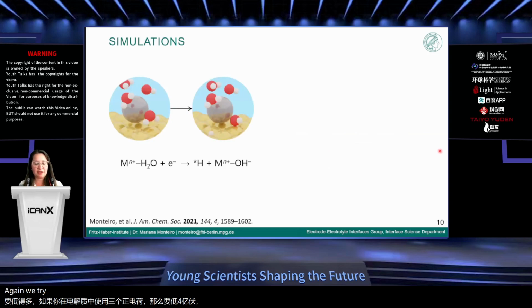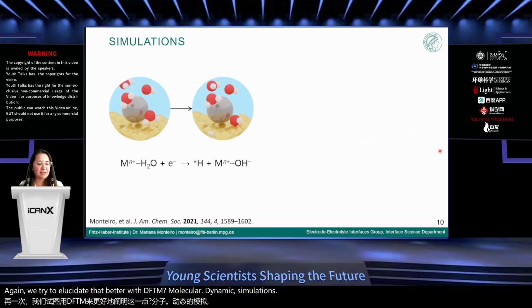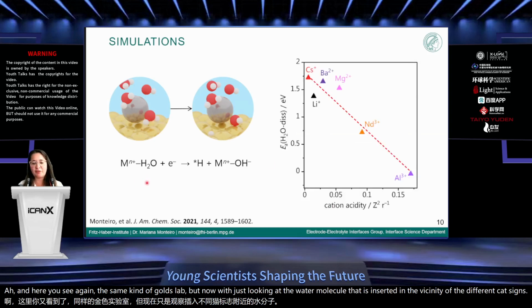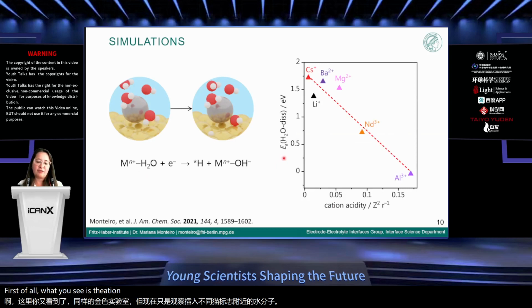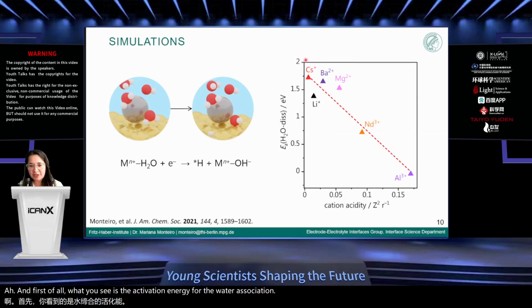Again, we tried to elucidate that better with DFT and molecular dynamics simulations. And here you see again the same kind of gold slab, but now just looking at the water molecule that is inserted in the vicinity of the different cations. First of all, what you see is the activation energy for the water dissociation. And contrary to the hydronium, you see that now it's not really a favorable step, and that's actually on gold believed to be the rate determining step for evolving hydrogen. And you also see that the barrier is much lower if you have acidic cations like aluminium, in comparison, for example, with the very non-acidic cesium.